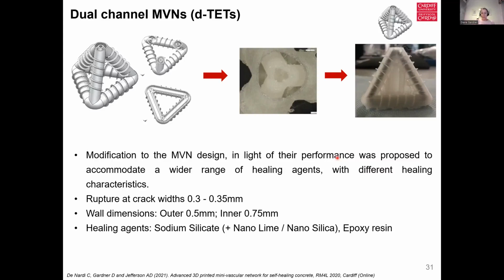And what we needed to do to achieve this was actually tweak the printing process slightly. We needed to make the ligaments a little bit thicker. We needed to make the wall thickness a bit thicker. We needed to provide internal supports to support the internal channels, and therefore these larger units tend to rupture at crack widths of 0.3 to 0.35 millimeters. The outer wall dimensions are 0.5 millimeter. The inner are a little bit thicker at 0.75 millimeters, and that's really to make sure that that inner channel is impermeable, to really make sure we are securely encapsulating that inner component.